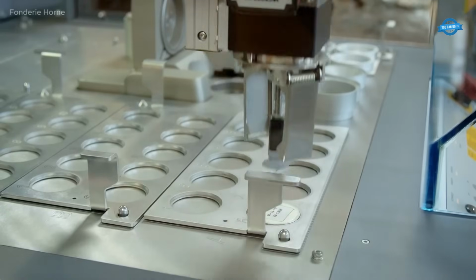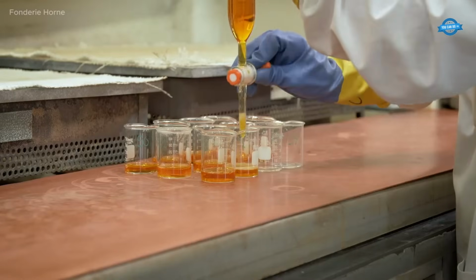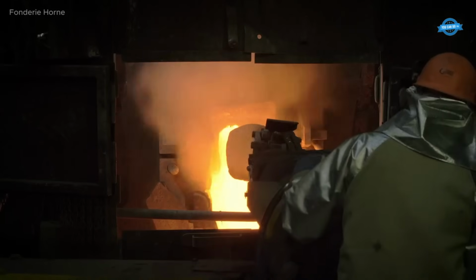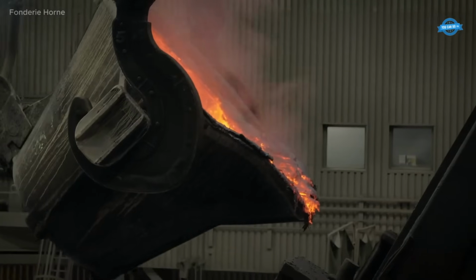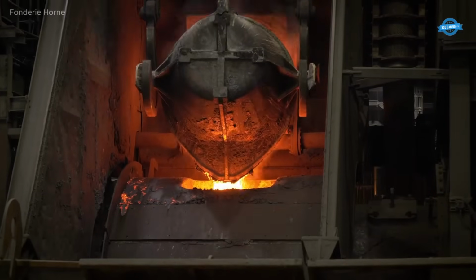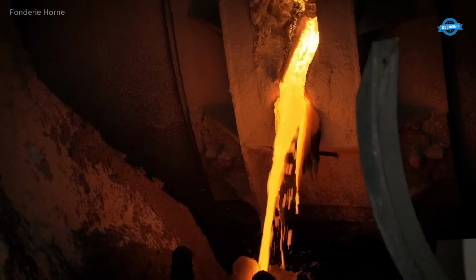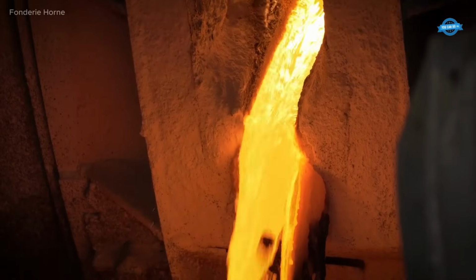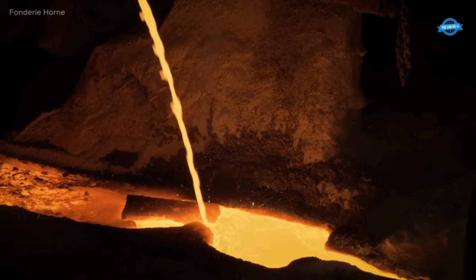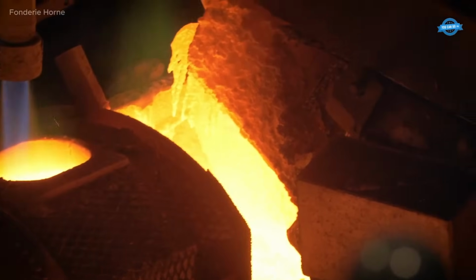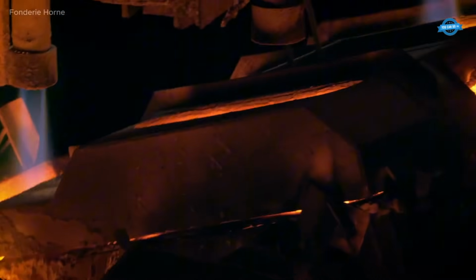The copper then undergoes additional purification in the desulfurization vessel at 1,200 degrees Celsius, removing sulfur traces. The final product, 99.1% pure copper, is cast into solidified anodes, which are cooled with water.